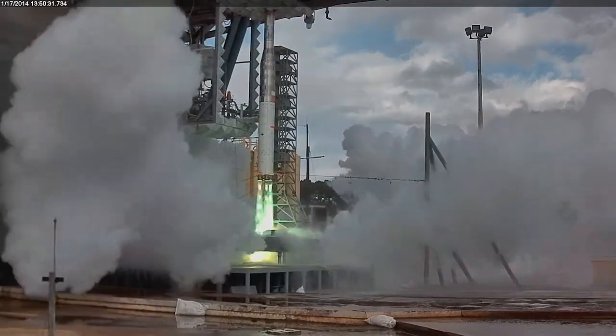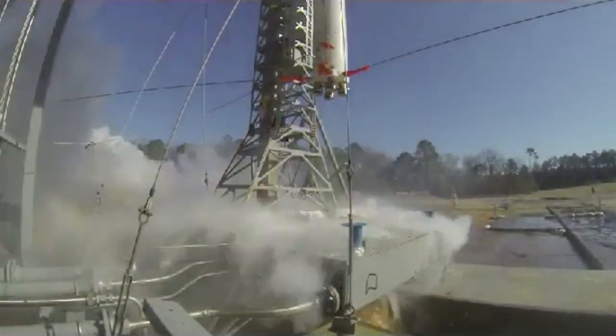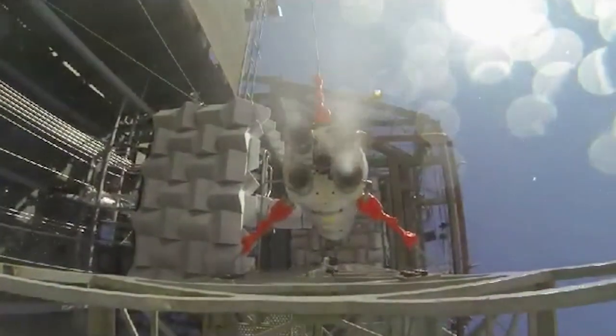With this process, we actually fabricated these in-house in one piece, so we got rid of all 32 braze joints and all five welds. We've actually got over 20 hot fire tests done on these units on the acoustic models so far. And as far as performance goes, they have the same performance or even better performance than the traditional injectors. They've held up really well — after 20 tests, we haven't seen any degradation of the parts.